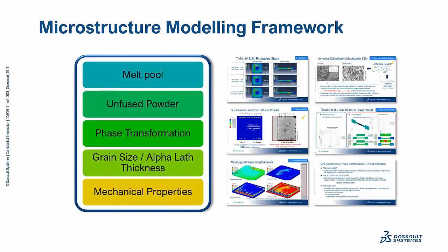On the micro level, we're looking at effects like melt pool behavior, prediction of unfused regions, unfused powder, phase transformation, changing the material properties during the build process as a function of the process, temperature, time, and so on, grain size, and then things like the mechanical properties for the full-size part. While we're not going into details at this point, I just want to show these slides showing that we can incorporate the process, and we've successfully been able to predict unfused powder regions. That's shown in this center image. We have an evaluated and validated framework for phase transformation simulation, which is part of the simulation that we offer. And we can use this information to predict mechanical properties from the micro model shown here onto large-scale full-size models.